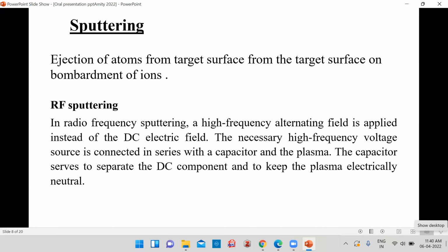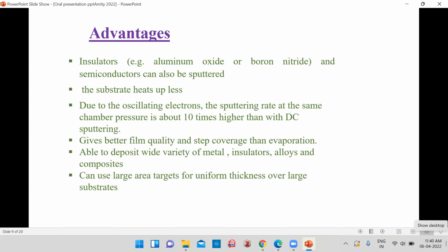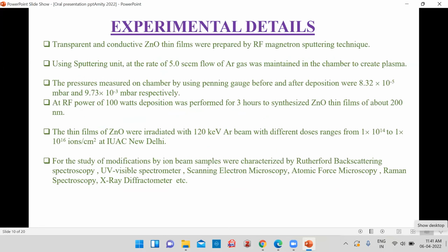Why do we use RF sputtering for our thin film deposition? The basic advantage is that insulators, semiconductors, etc. can be sputtered. The substrate heats up very little. Due to the low oscillating electrons, the sputtering rate is very high compared to DC sputtering. It gives better film quality, is able to deposit a wide variety of metals, insulators, alloys, and composites, and can give a large area target for uniform thickness over the substrate.